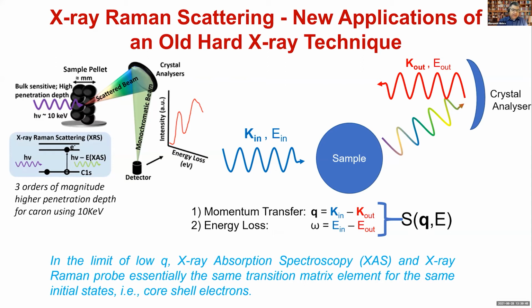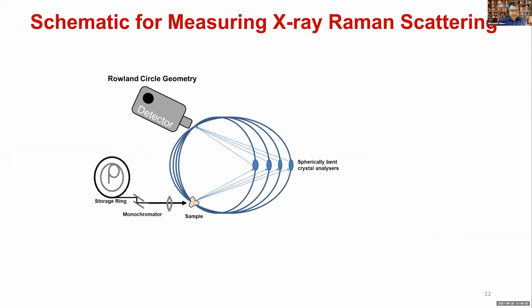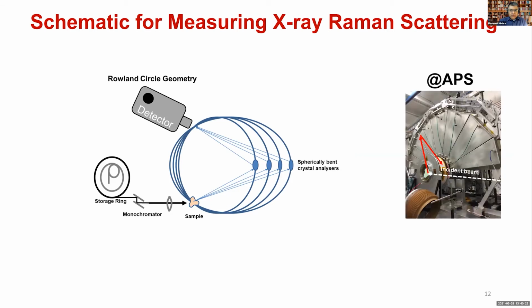The main advantage here is that X-ray scattering has three orders of magnitude higher penetration depth, for example, if you use 10 keV instead of 280 eV. The schematic of X-ray Raman scattering works as follows: the beam goes through a monochromator and so on, and then finally the light is shone at the sample, which strikes one of these crystal analyzers, scattering the photons, and they are ultimately collected by a detector, and the energy loss is plotted. This is a schematic of how it is done at APS in sector 20.